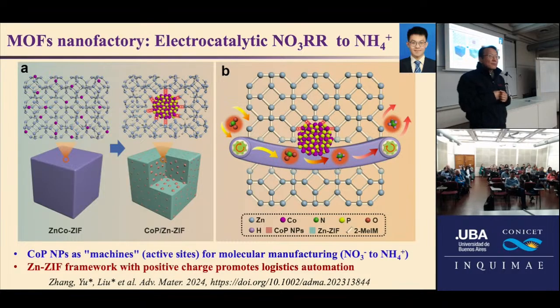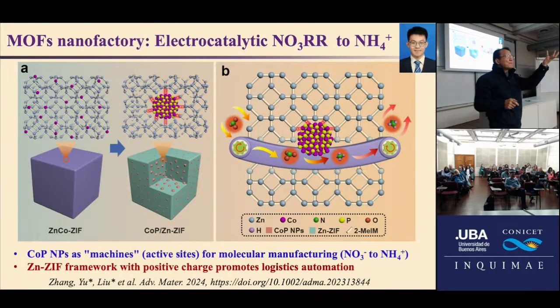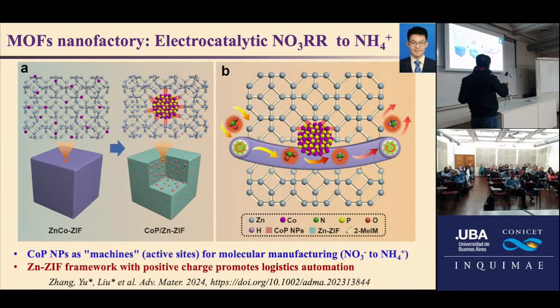So the MOF anisotropic design has multiple advantages. This is one example. We have an in situ conversion method. We start from a cobalt-zinc ZIF-8 structure, then have an in situ conversion of cobalt into a cobalt phosphorus active center, and then use this electrocatalyst for nitrate reduction to ammonia. The advantage is that this positively charged ZIF-8 framework can provide an electrostatic interaction towards the negatively charged nitrate, and then discharge the positively charged product, which is ammonia.